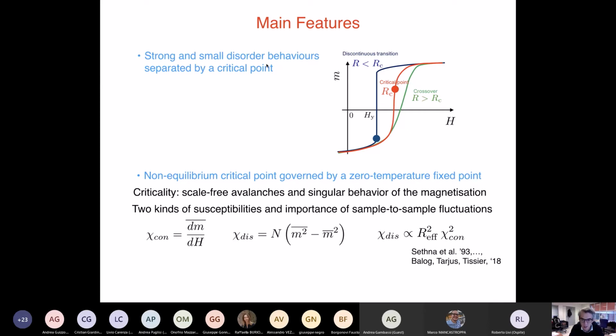One of the key features of this is that you can compute two different susceptibilities. One is called the connected susceptibility, which is just the derivative of the magnetization with respect to H, averaged over the disorder, where the overline is the average over the disorder. Or you can compute the fluctuation of the magnetization with respect to the disorder, which is called the disorder susceptibility. When you have a critical point governed by a zero temperature fixed point at which the disorder is very important, the disorder susceptibility is related to the square of the connected susceptibility times a prefactor, which is the effective strength of the disorder at large scale. This is what you find in all zero temperature critical fixed points. So this is just to tell you that there is an interesting critical fixed point that separates the two phases. These are the first two key features, and there is another one.